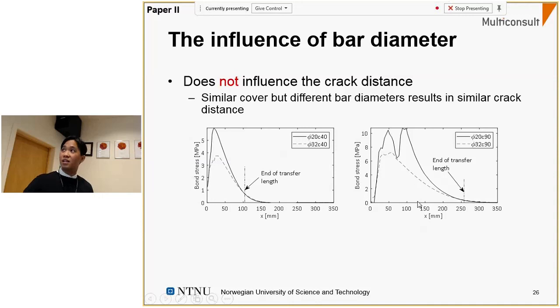What we see in these graphs here is that the mean bond stress is not constant and that it varies depending on your bar diameter. So the assumption that the mean bond stress is always constant regardless of your bar diameter is not correct compared to what we see from these virtual experiments, which has also been verified in the literature. You can also see from experimental results in the literature that if you have different bar diameters but the same cover, they still result in the same crack distances.